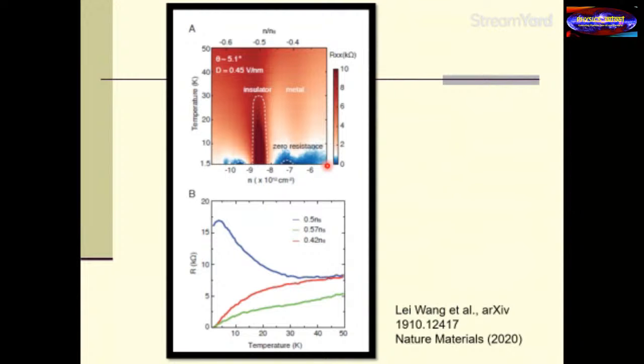So why is this system behaving in this unusual way? And this is also reflected by these plots over here, where you can see that depending on my hole concentration, the resistivity, if you've come across it in your courses, if you've seen what the resistivity as a function of temperature looks like, these are typical behaviors for metallic cases, whereas over here you have this sudden rise, which is indicating that it has some kind of band gap associated with it, like a semiconductor. Okay.